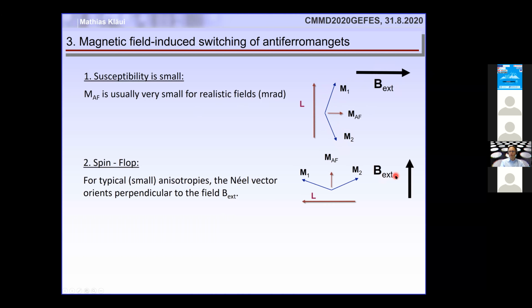However, if we rotate a field, then even though the two sublattices cant very little, it is still advantageous for the two sublattices to be in a direction that is perpendicular to the applied field, so that the little induced moment by the canting is parallel to the applied field. And that's the so-called spin flop field, which I showed you when we discussed the energy scales, and it can be of the order of a few Tesla. So this is something we can do in the lab.